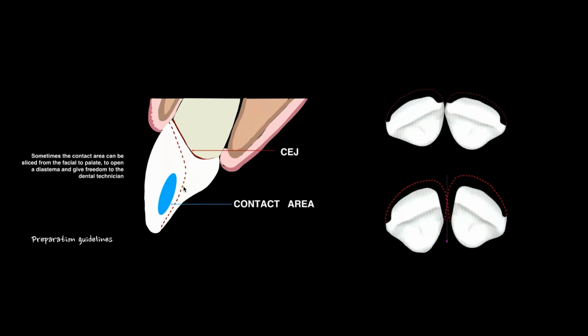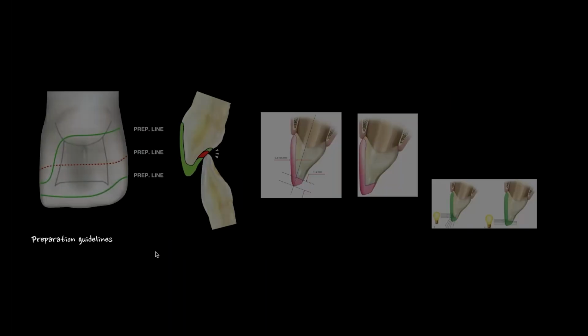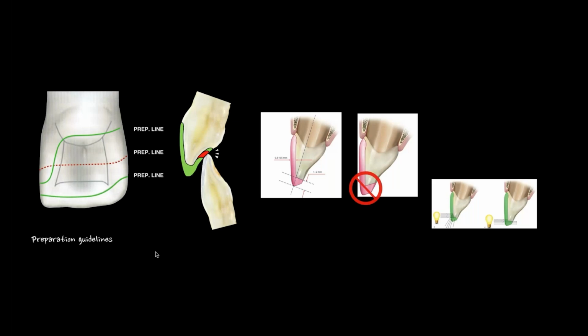The other thing that I would tell you is on these minimally invasive cases, if you look at the finish line on the incisal edge, I really want my finish line to be a true shoulder preparation, and the reduction is 1 to 2 millimeters depending on the type of tooth and the aesthetic parameters we're looking for. The minute that I see cases where you need more reduction, where we're looking at a prep finish line of here, which should be normal.